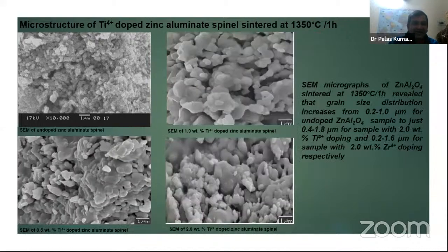And if we see the titanium, again with increasing titanium concentration, the grain growth and its distribution gradually increase. Especially for titanium, up to 0.5% the regularity is maintained, but from 1% some abnormality started, and for 2%, both 2Z and 2T are completely different. But it is very clear that for zirconia dopant up to 1% and for titanium up to 0.5% the structure is very regular.